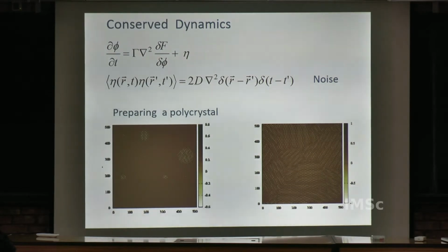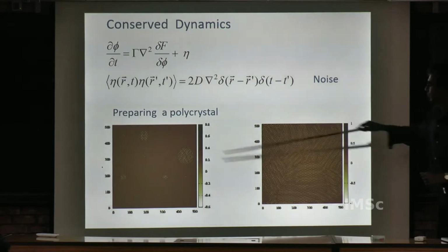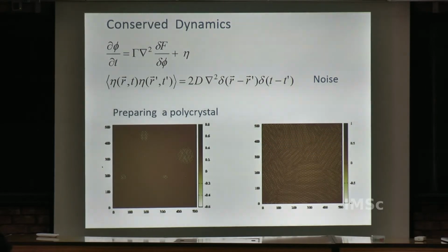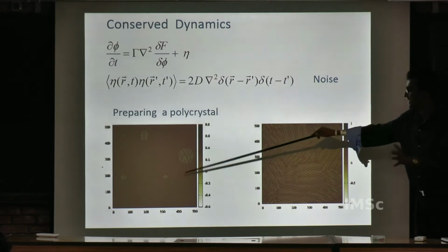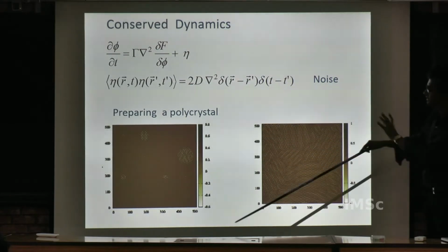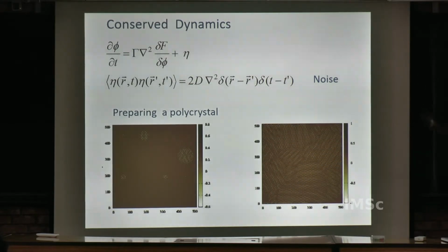Now this has been specially created. If you just take one nucleus, and set an initial condition which is liquid like, let's say all constant, phi is constant, but you choose the parameter so that your equilibrium phase is a triangular lattice, and then you put a nucleus like this by hand and let it grow, you will find that the whole system just fills up with a single triangular crystal.